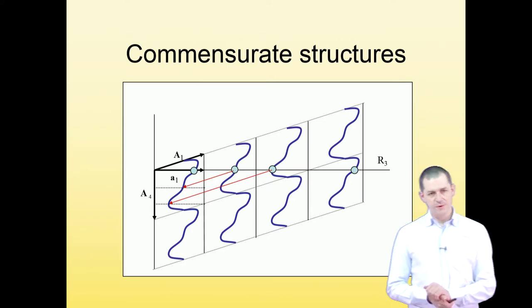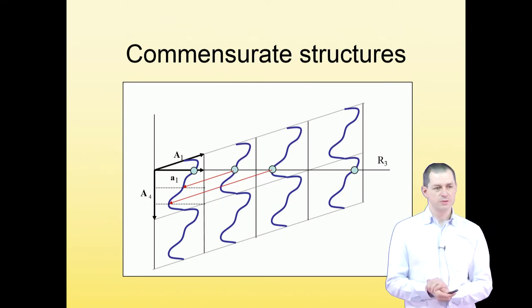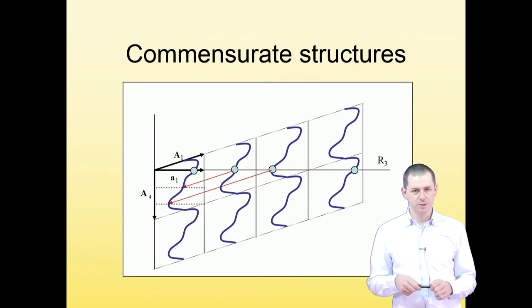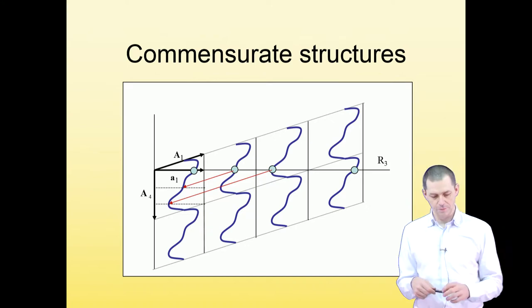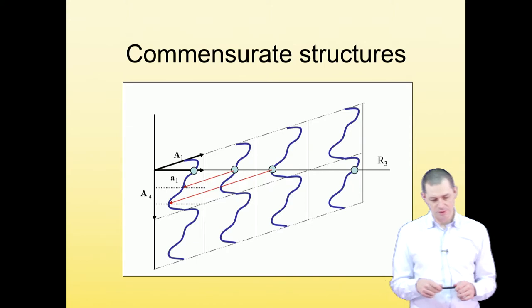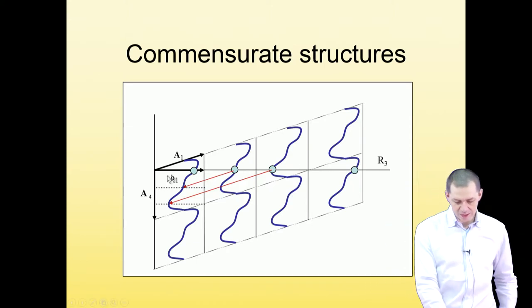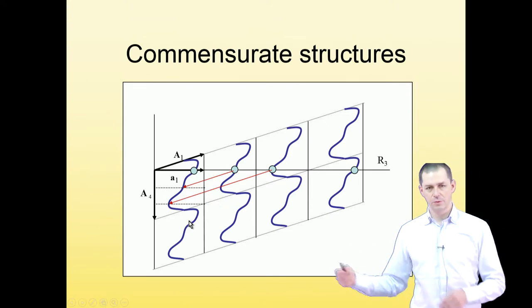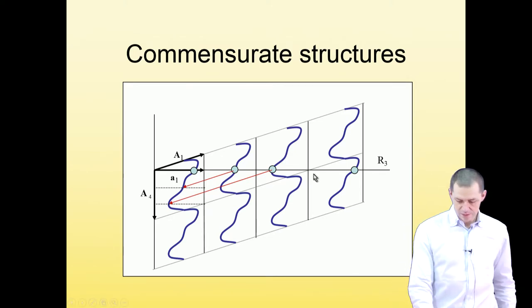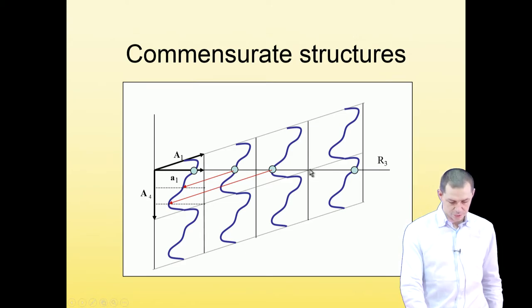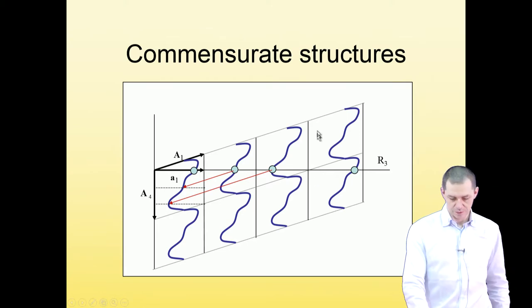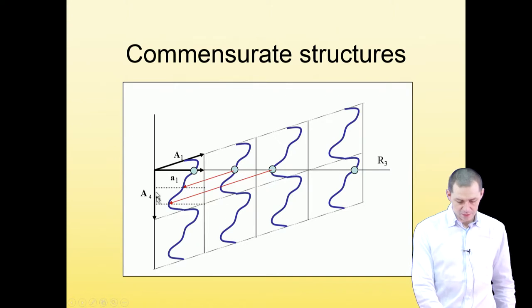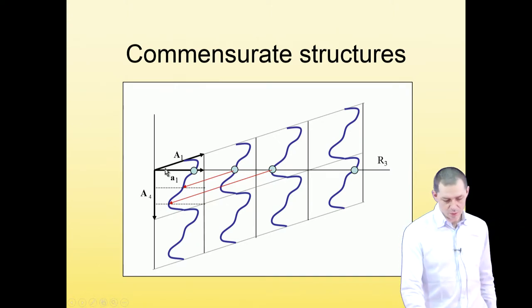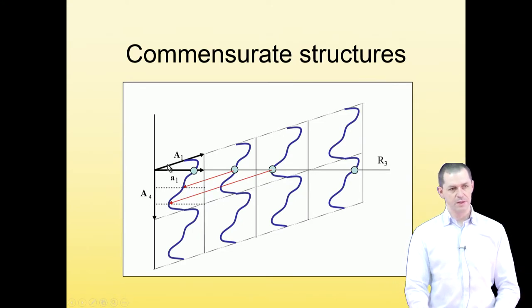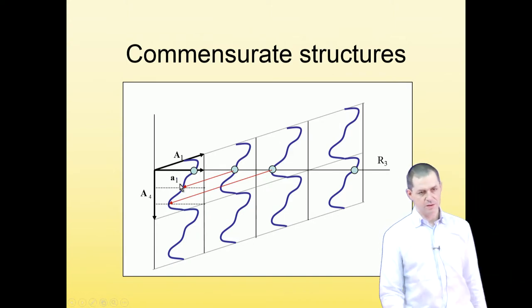The commensurate structures have certain specifics, and although it may seem that they are easier than incommensurate structures because they are, in the end, periodic, the superspace description is somewhat more complicated. You need to take care of a few things that you do not need to do in an incommensurately modulated structure. But the key point is that instead of having infinitely many t-sections describing infinitely many different unit cells in an incommensurate structure, here, this is a model for a commensurate structure. So here you have a perfect intersection of the physical space with the node or corner of the unit cell in superspace. And therefore, from here on, you get the same section here as here. And in the first unit cell, you actually get only three different sections. So only three sections in the superspace unit cell are physically meaningful. All the rest is not, and it is never realized in the commensurate structure.